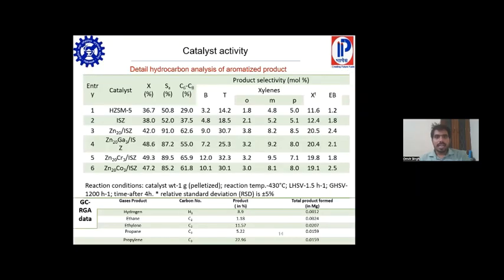Then come to catalytic activity for the aromatization reaction. I have done the catalytic reaction using different types of imidazole supported catalyst. From them we found the imidazole supported catalyst shows good performance as compared to ZSM5, and after the addition of a different bimetallic, the conversion and aromatic selectivity is increased, which is due to the increase in acidity after loading of a different metal. Then come to RGA. We found different gases like hydrogen, ethane, ethylene, propane, propylene, which were formed during the reaction, which were detected by RGA.